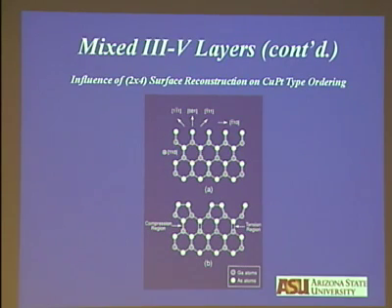So to lower the electronic energy of the system, you form dimers, as shown here. And we have done valence force field calculation to illustrate. Underneath the dimers, the arsenic bonds to arsenic to form a double bond, and there is a compressive stress region. In between the dimers, you have a tension region.